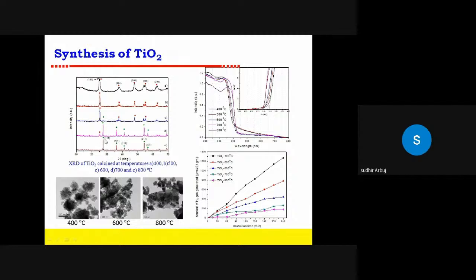What does it indicate? It indicates that TiO2 is in the anatase phase up to 400 and 500 degrees centigrade. Then at 600, the anatase phase starts converting to rutile phase. At 700, almost 90% is rutile and 10% anatase, and at the higher temperature of 800, only the rutile phase is observed. So from this study we can judge that up to 600 the anatase phase is stable, and above that the rutile phase starts existing.